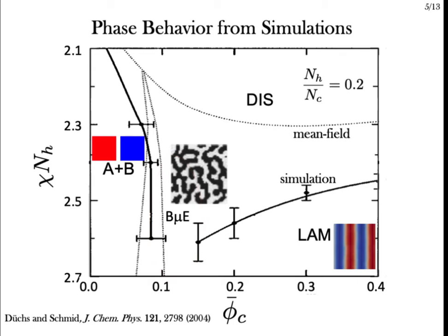Although the simulations shown here were a leap forward, and they qualitatively capture what's seen in experiments, this is by no means the end of the story. They were done all the way back in 2004 when computational resources were not as available as they are today. They were also done in 2 dimensions. Dimensionality is an important consideration in critical behavior, so the critical point that they located may not be accurate. Bicontinuous microemulsions are also an inherently 3-dimensional structure, so can't adequately be captured in 2 dimensions.